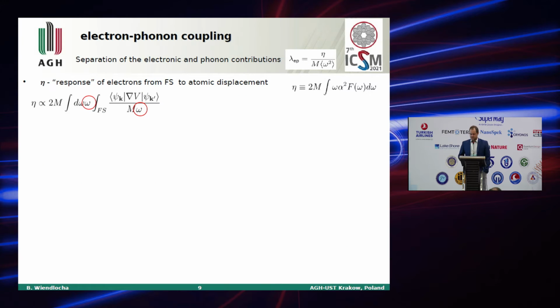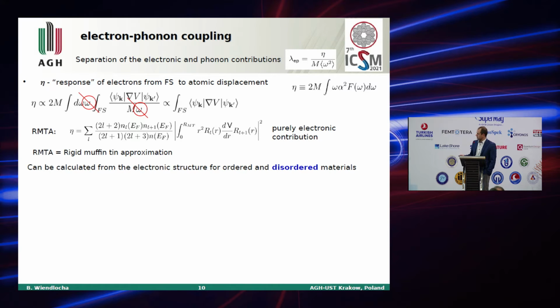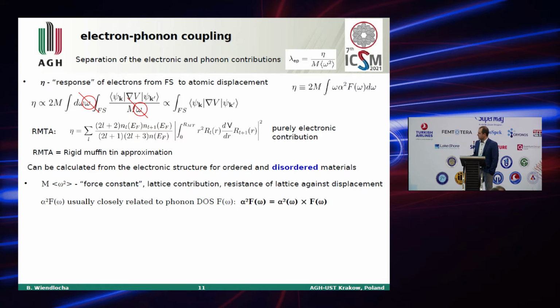The benefit is that if you look more closely at the McMillan-Hopfield parameter, you will see that because the Eliashberg function is multiplied by the phonon frequency, this phonon frequency cancels out here. So this is a purely electronic quantity which may be calculated, after some additional simplifications, basically directly from the electronic structure. So we don't need to know phonons to get the McMillan-Hopfield parameter, so it may in principle be calculated also for disordered materials. And the second part, the denominator, looks like a force constant, so this is like a lattice contribution to electron-phonon coupling.